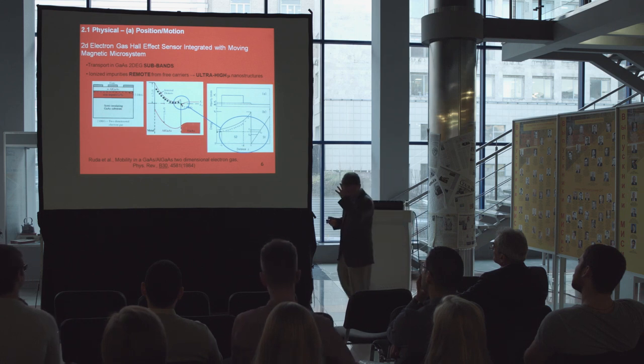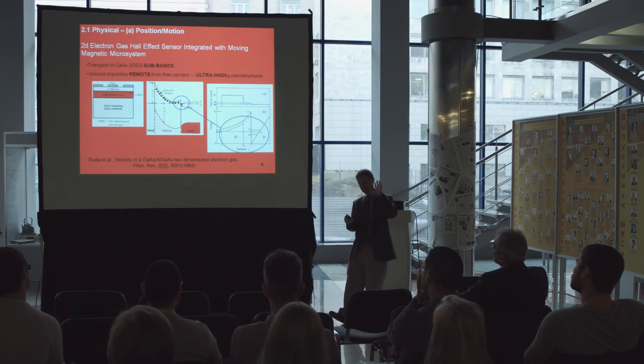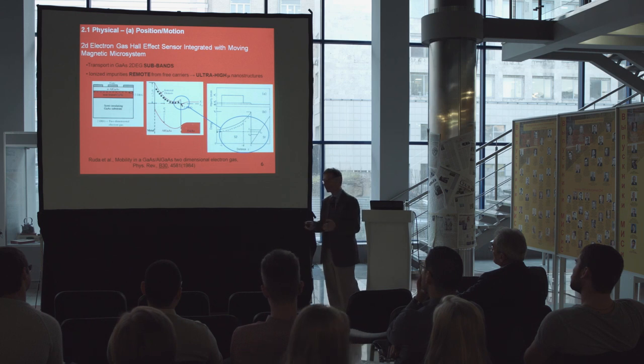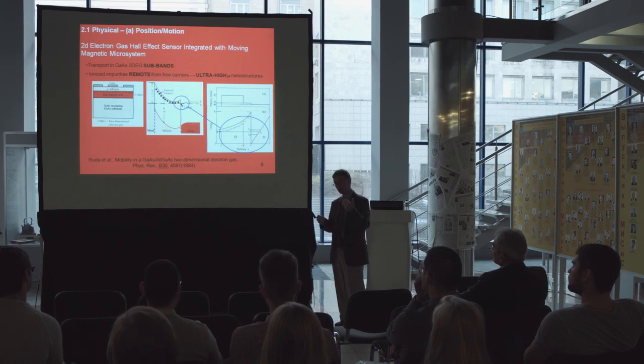Because one of the things that defines a perfect interface is lattice mismatch. When the atoms on one material and the atoms on the other align, the lattice constants actually, the strain at the interface is minimal. Actually, it's basically zero here. So the tendency for defects to form, particularly dislocations, which will hold charge and form non-radiative recombination centers, is